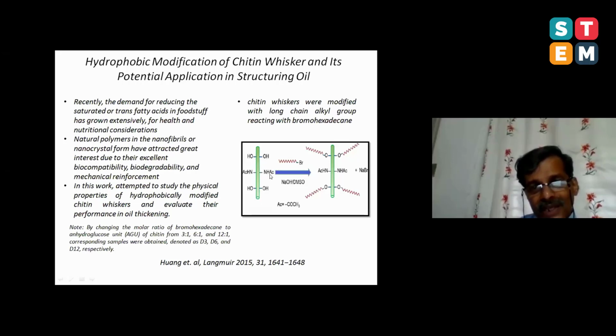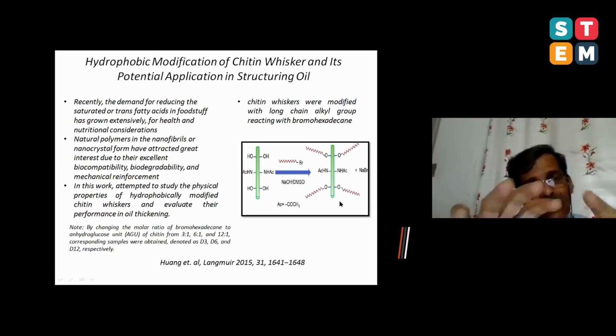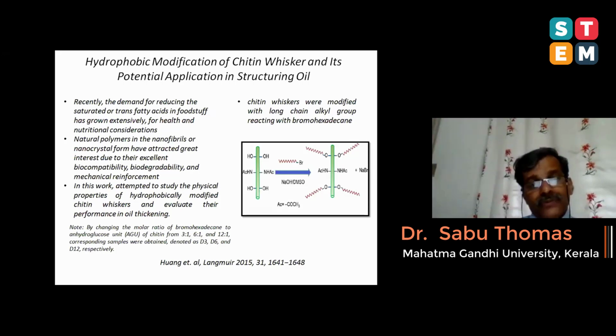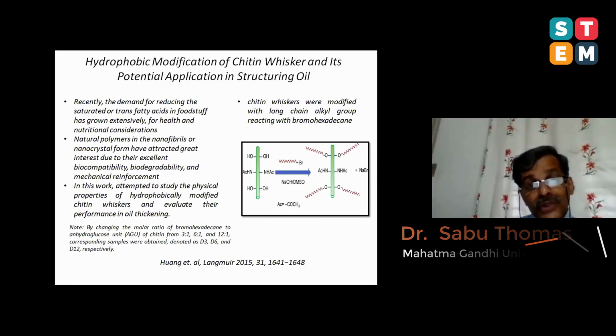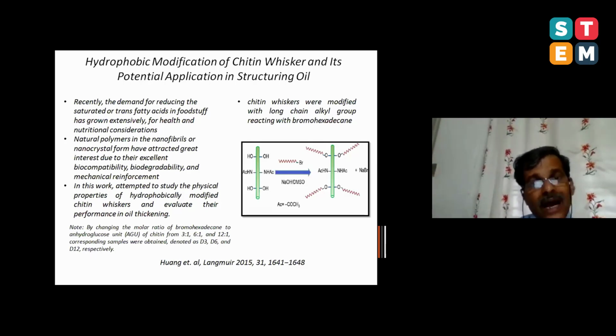You have hydroxy group, you have NHAc group. And what they did is, by a very simple chemistry, they put lots of hydrophobic groups on the surface of these chitin nanocrystals. These are all hydrophobic groups. If you look at it, nanochitin is essentially hydrophilic. So they made the surface hydrophobic by putting hydrophobic groups. When you incorporate such alkyl groups on the surface of nanochitin, you can make them hydrophobic. By controlling the chemistry, by controlling the length of this alkyl chain, you can control the hydrophobicity.